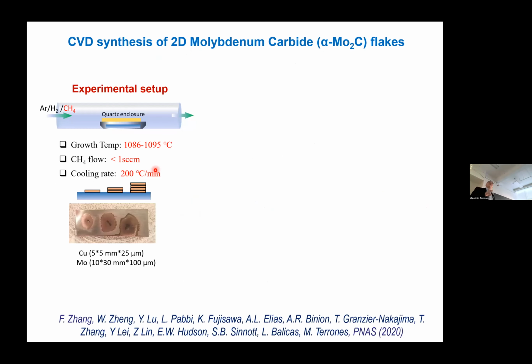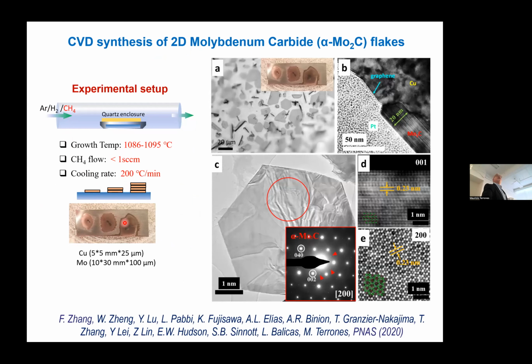The way we grow the carbides, and this is alpha molycarbide, is very simple. In this case, you use copper and moly foils on silicon oxide, and then you just flow methane with argon. You have the copper molten on the moly, and then you have the growth of the carbide, and then you can just remove the copper. And then what you get is very thin carbides. These are beautiful. This is moly alpha carbide, and you can see these beautiful shapes.